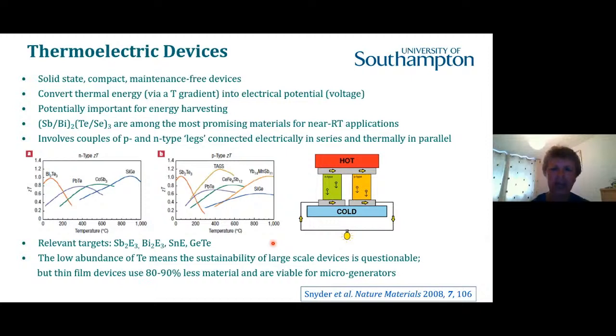On the other hand, if we use thin films, we will get less power out, but that means we can focus on particular application areas using these as micro generators, but we use almost 90% less material. So the use of tellurium then becomes viable. And of course, we can think also about more sustainable solutions by replacing tellurium with selenium or some sulfur and optimizing the properties. So there's a very nice review from Snyder in Nature Materials just over a decade ago, which sets the scene nicely in this field.